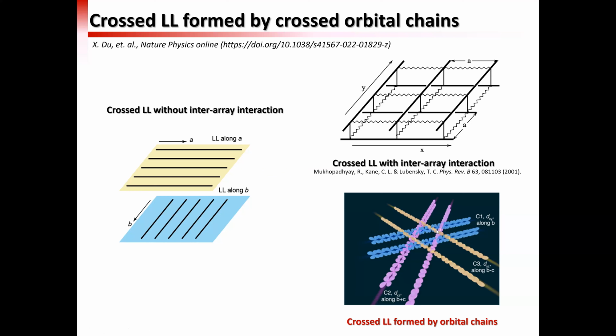We call them orbital chains, and there are three groups of them. These three groups cross each other, and interestingly they have weak interaction between them. This realizes the crossed Luttinger liquid model that was proposed by Charlie Kane and his collaborators about 20 years ago. So this is a very interesting model system that may generalize Luttinger liquid behavior into higher dimensions and may be used to explain some strongly correlated phenomena in higher dimensional materials. The next thing we would like to do is certainly to explore whether there are some topological properties in this kind of Luttinger liquid chains.